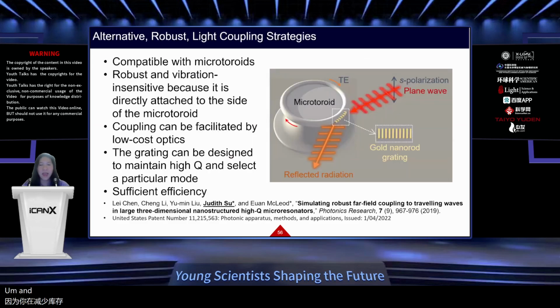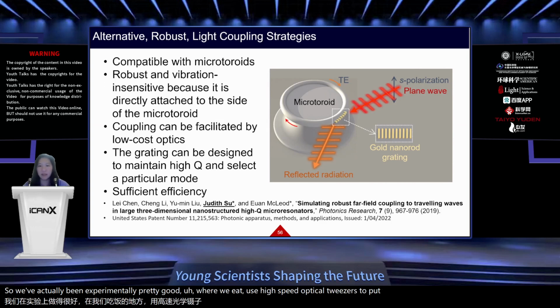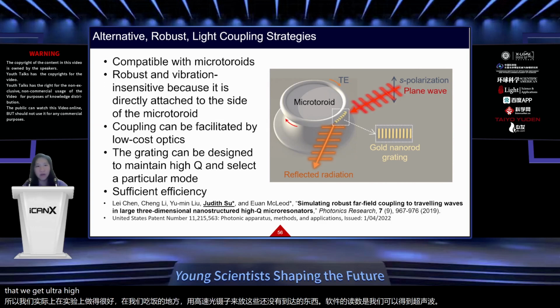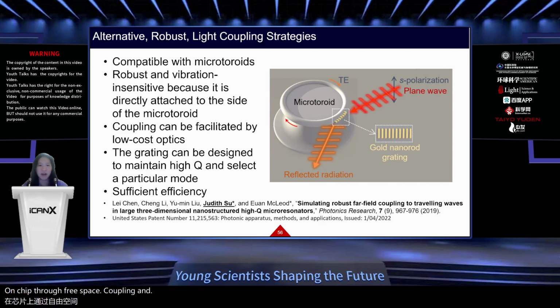And then we've been looking at alternative robust light coupling strategies. We've actually been experimentally implementing this, where we use high-speed optical tweezers to put these nanorod gratings on the surface of the toroid, so that we can get ultra-high Q cavities on chip through free space coupling, and we don't have to deal with environmental disturbances like the taper moving against the toroid, which can cause noise in our signal.